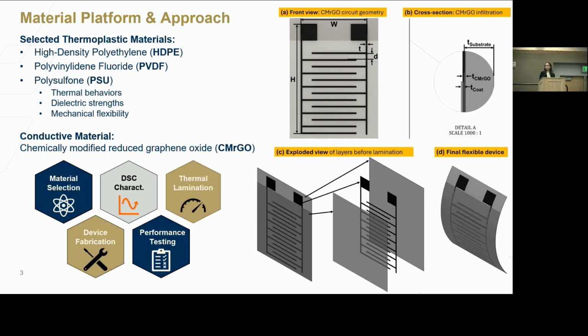And since we've already been using a thermoplastic substrate, we decided that a simple thermoplastic attachment method would be effective to address this issue in an adhesive-free manner. Now, on this image, you're going to see our design that consists of two interdigitated electrodes of CMRGO. And on the cross-section, you're going to be able to see the particle infiltration of CMRGO from both a thicker substrate layer and a thinner coating layer.